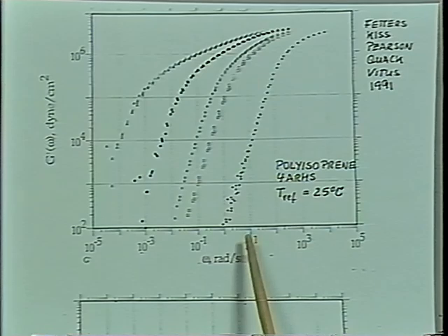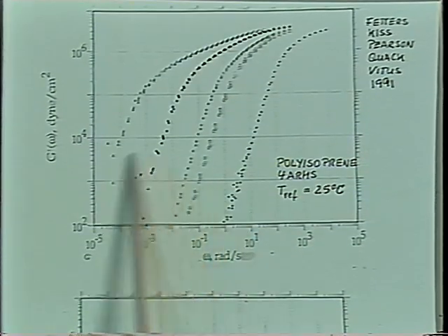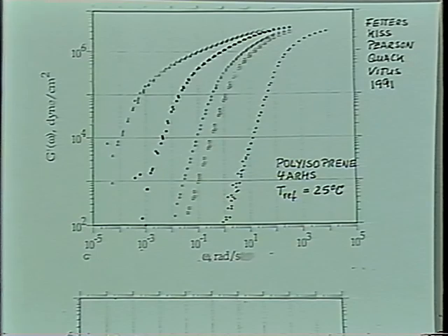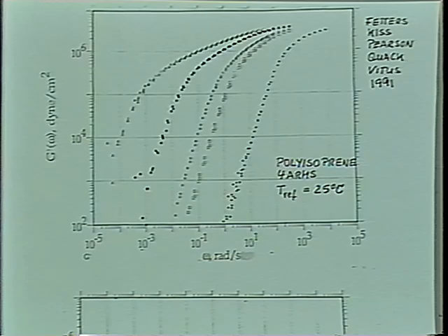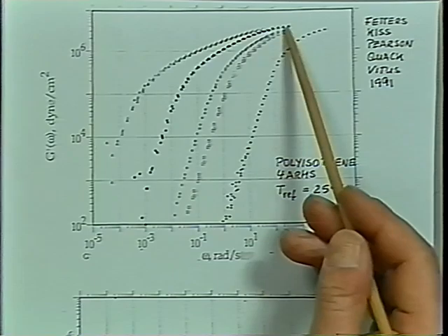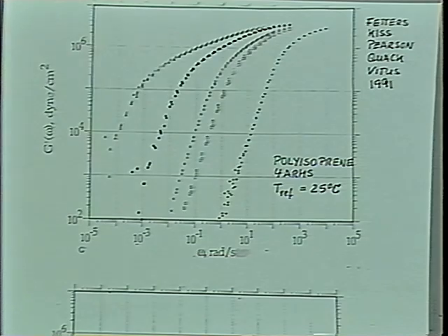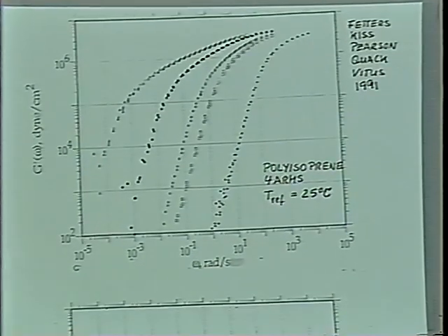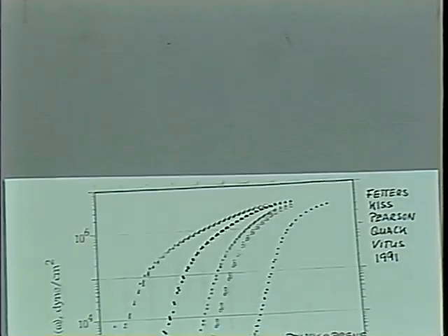It's not clear what the molecular weight of those stars was, because in the table there are 8 species, and I only have 5 of the data curves, so I don't know what Fetters meant here. But interesting enough is the shape of the curves. There's somehow a power law region coming in. Look at this. It's a straight line here, but it is not really a power law. If you take the spectrum, this would be now G prime, and I have G double prime, I believe, here.